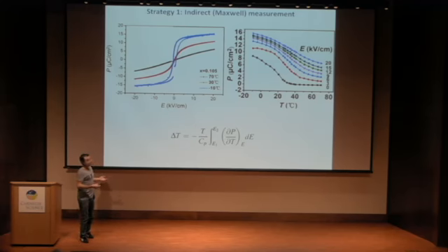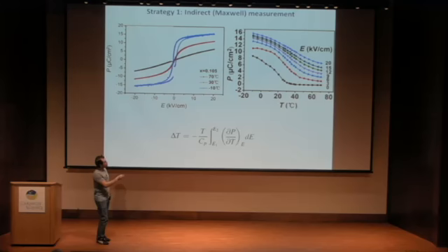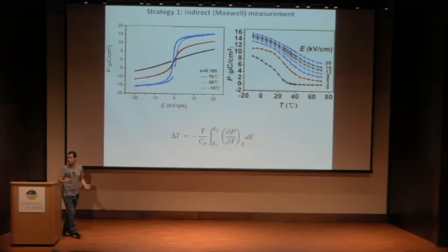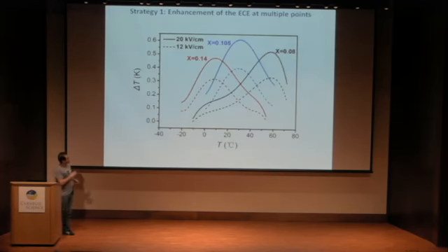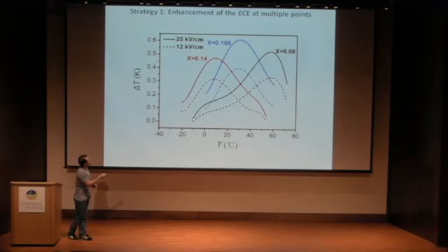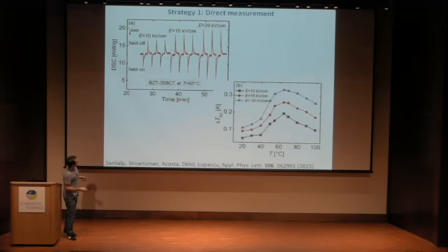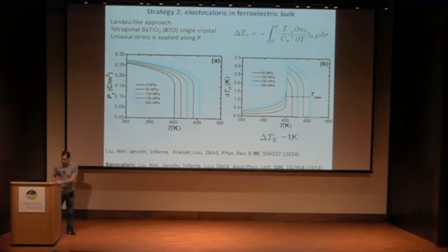We can see that in that case, we have a nice ferroelectric system in the sense that we have the polarization, which is decreasing with temperature and goes to 0 at the critical temperature in the paraelectric phase. So we can extract this delta T. Then you can see that this delta T is not so huge, but this composition is highest than the others.